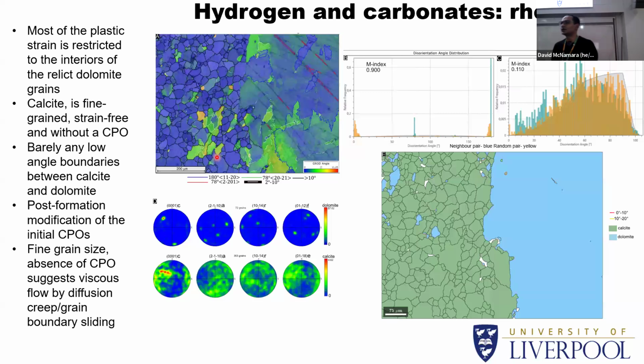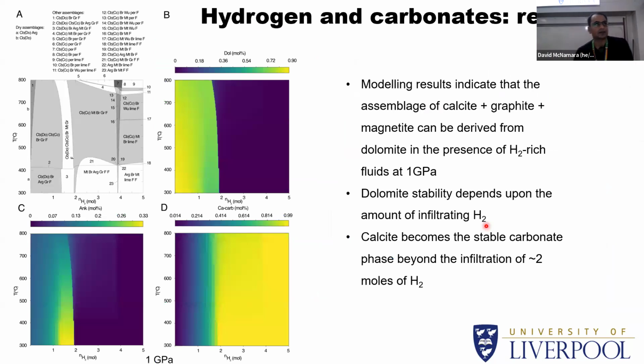So suddenly, once you form the calcite, you are creating zones where you have accelerated strain rates and very high strain partitioning into these layers. What is also noteworthy is we do not see so many low angle boundaries between the calcite and the dolomite, except where you have these islands of calcite in dolomite or islands of dolomite in calcite. But probably this is due to the fact that you disrupt the initial orientation. So once you get the calcite layers to flow, you are disrupting the initial orientations that you had.